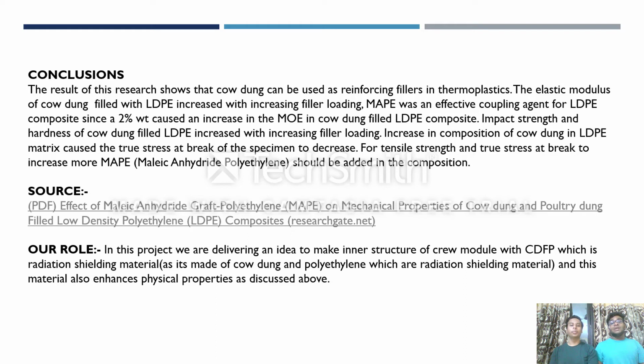So now, impact strength and hardness of cow dung filled LDPE, which is low density polyethylene, increased with increased filler loading. Increase in composition of cow dung in LDPE matrix caused the true stress at break of the specimen to decrease. For tensile strength and stress at break to increase, more MAPE, which is maleic anhydride polyethylene, should be added in the composite. So now all this information and all this research material we have got from the source, and we have attached it below.